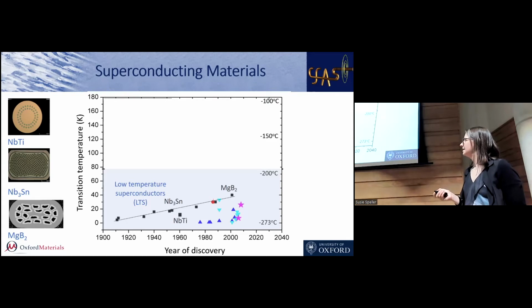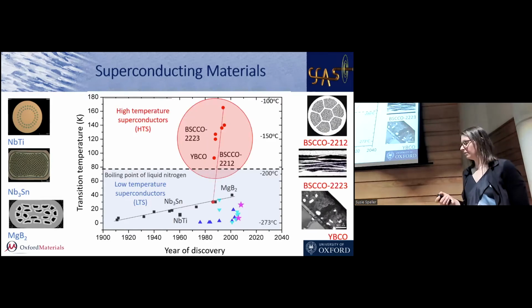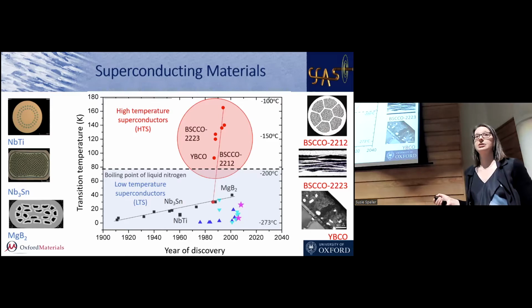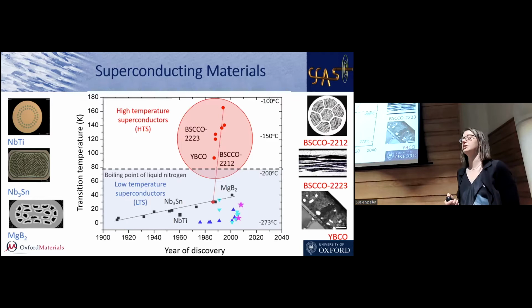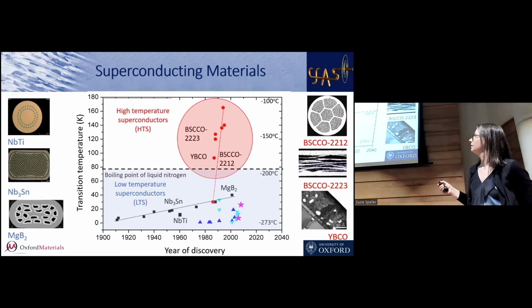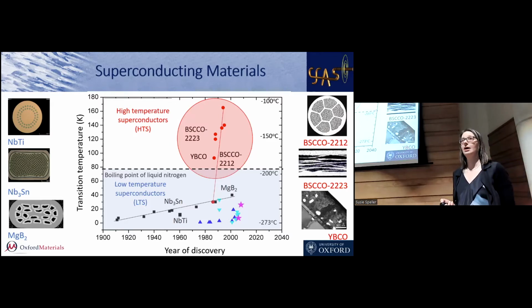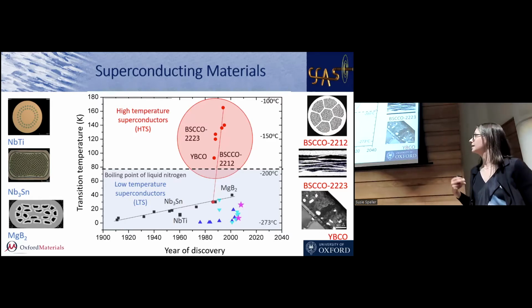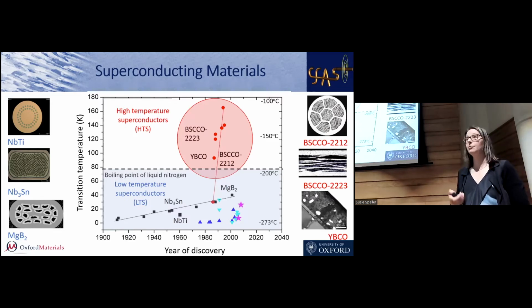However, in the late 1980s, a new discovery was made that was very surprising because nobody thought you'd be able to get superconductivity at such a high temperature. But a whole new family of compounds, which we now call the high temperature superconductors, which are based on copper and oxygen, so they're oxides, were discovered. They've got critical temperatures much higher and, importantly, above the boiling point of liquid nitrogen, which is 77 Kelvin. And liquid nitrogen is much cheaper and easier to cool. So as a cryogen, it's much more viable for lots of commercial applications.